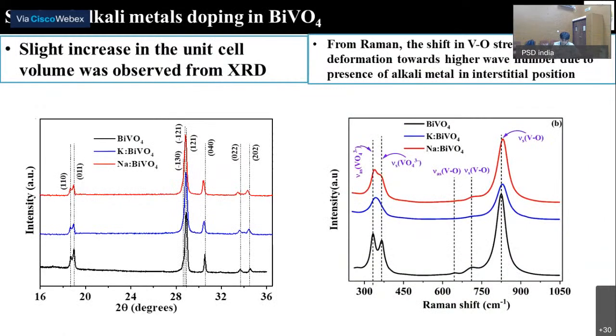Now further, how this behavior is correlated with the crystal structure of this doped bismuth vanadate has been analyzed using the XRD technique. In the XRD, we did the Rietveld refinement also. With that, we have seen that there is a slight increase in the unit cell volume. So that suggests that the dopant we are putting in the bismuth vanadate system might be going to the interstitial positions. And further, the Raman spectra also confirm this: the increase in wave number towards higher shows that our bonds are weakening.